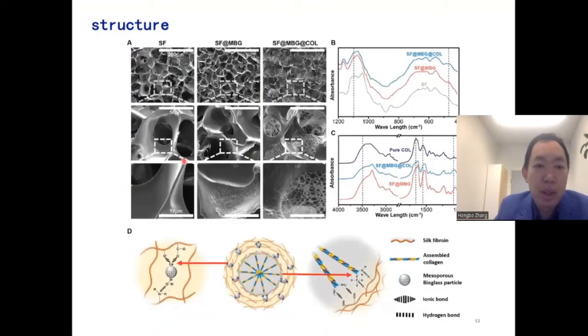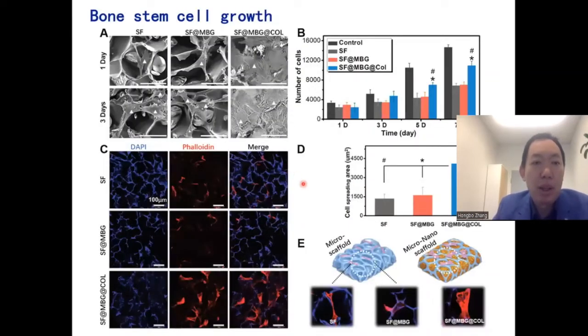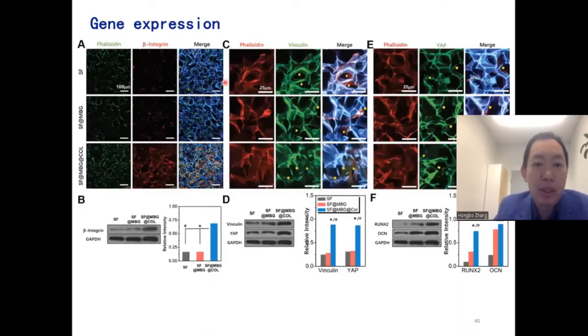So as you can see in these pictures, this is a fiber, and the one seeded with this bioglass, and then with collagen network. So after we build up such a structure, we culture cells on top of this scaffold. And clearly we notice that the better you mimic this structure, the better it can promote the bone stem cells to grow. And we test gene expression to see whether there are important genes expressed. And again, we find a similar finding that the better you mimic the structure, the better it can promote this positive gene expression.